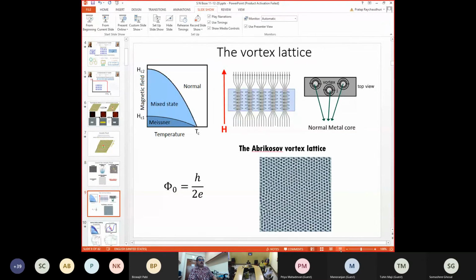Now, a very brief introduction. We know that if you take a type 2 superconductor, then it's a perfect diamagnet at small field, but above a characteristic field, Hc1, the magnetic field can enter the superconductor in the form of flux tubes. These flux tubes are often called vortices because they have a circulating current around them which sustains this magnetic field. And each of these flux tubes carries a flux which is quantized, and it is one flux quantum given by this universal constant h by 2e.